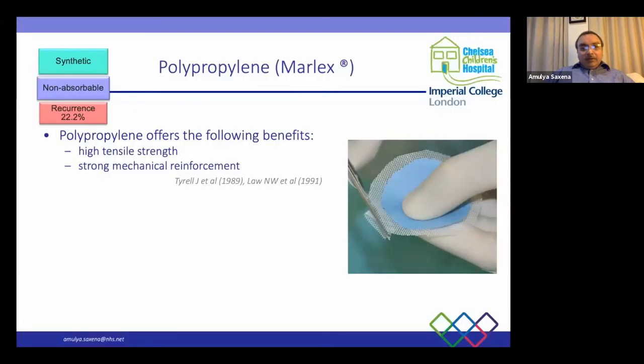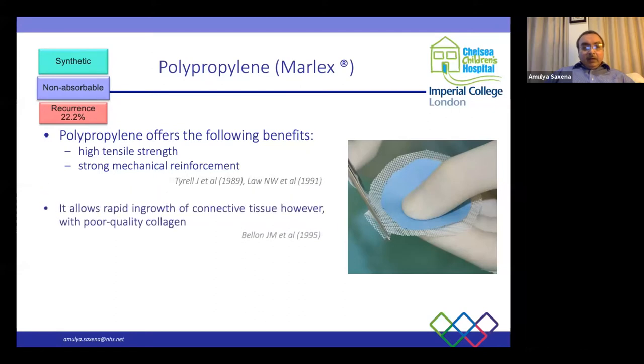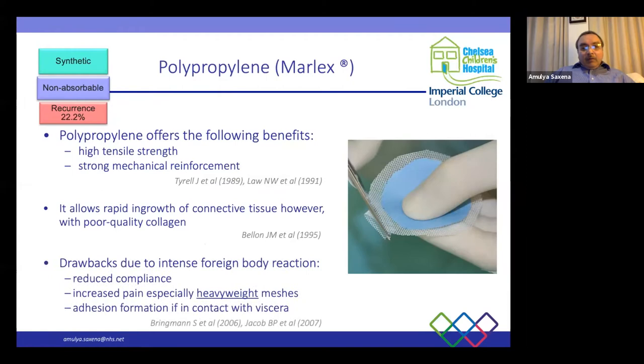Now, polypropylene mesh is, as you can see here, a Marlex mesh. It's a synthetic material. It's non-absorbable. It has a recurrence rate of 22%. Now, it offers the benefits of high tensile strength and strong mechanical reinforcement. It allows rapid ingrowth of connective tissue. However, please bear in mind, this is very poor quality of collagen that grows inside these. The drawbacks are in the foreign body reaction because of reduced compliance. There's increased pain if you use heavyweight meshes.